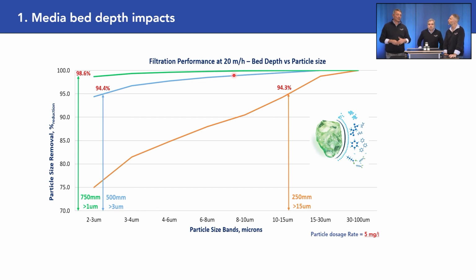Well, for media filtration, we say there are 3 factors which are impacting it. One of them is the media depth. What you see, maybe you can quickly show, on the x-axis you have the size of the particles from 2 micron to 100 micron, and on the y-axis you have the removal rate from 100% to 70%, how much you remove. And we have tested here with 20 meters per hour, or 20 cubic meters per square meter per hour. That's the same thing.